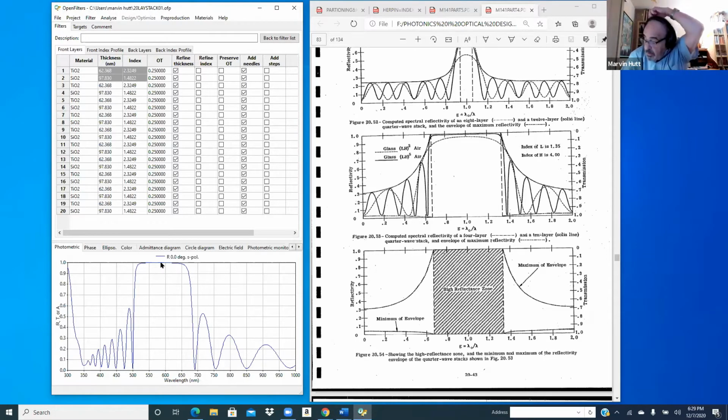With me? Found in all the lasers, typically 19 to 20 layers of 2 hard oxides, titanium dioxide and silicon dioxide, okay? So that they can withstand the vacuum inside the tube of the laser when they ignite the gases in the old days, right? Now, you notice the envelope here.